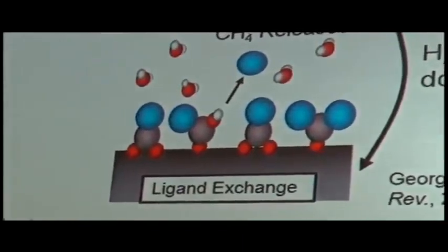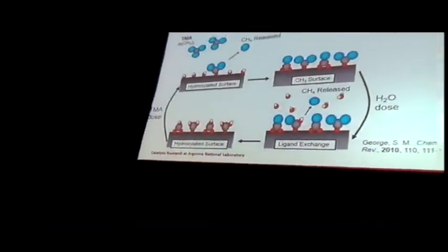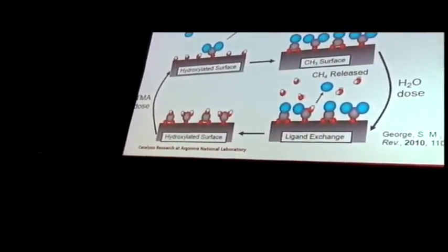In the case of TMA, what we do is feed in water. That then releases the rest of the alkyl groups, in this case methane, and generates new hydroxyl groups on the surface. Okay, and that then allows us to go through the whole series again, doing another layer, and so we can build up layer by layer onto the surface of the catalyst whatever we're interested in. We can change those materials partway through the synthesis to get mixed phases and a whole raft of other things we can do.